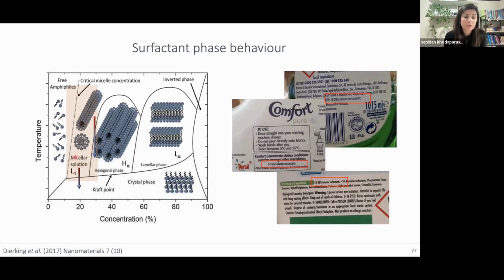But what I'm going to talk about is that when you decrease the temperature, you cool down your solution, you're going to go from these isotropic small micelles, these are nanoscale micelles, to these larger scale self-aggregations, which are in crystal forms. So if you cool down your liquid soap in the kitchen, in the fridge, you will start seeing crystallization occurring, and then you will have the precipitation of these crystals at the bottom of the container.